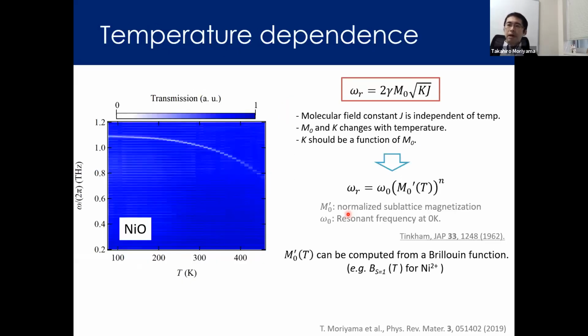Okay. And one other important data is the temperature dependence of the resonant frequency. Unlike the ferromagnetic case, antiferromagnetic resonant frequency does not change much by the external field. So it basically doesn't really respond to the external field. But its sensitivity changes with the temperature, something like this. In the nickel oxide case, the frequency drops rapidly above room temperature toward the Néel temperature. So this temperature dependence actually also tells us some important parameters.